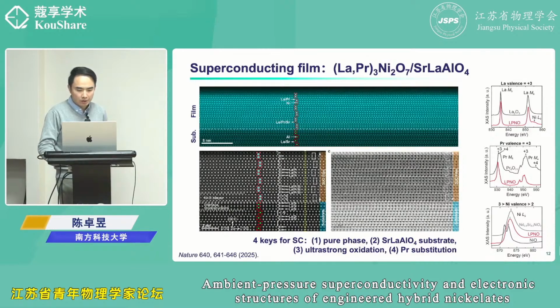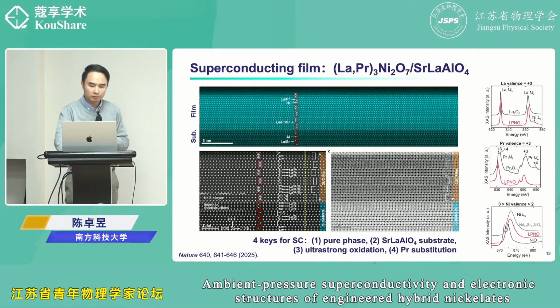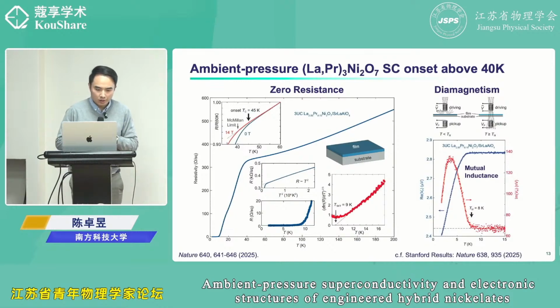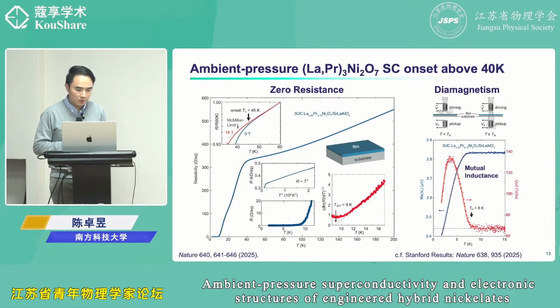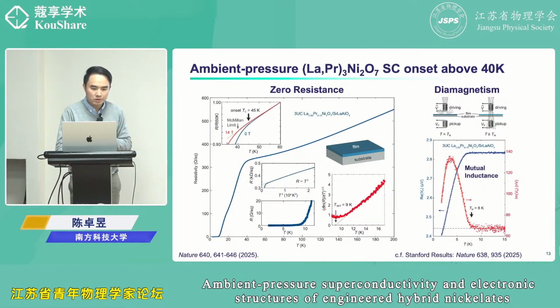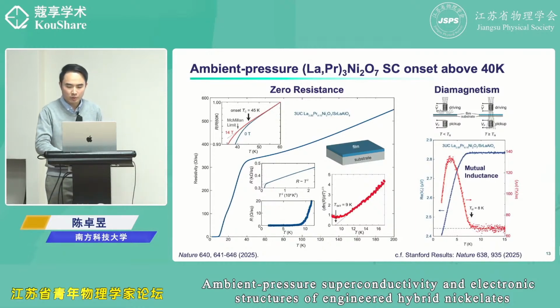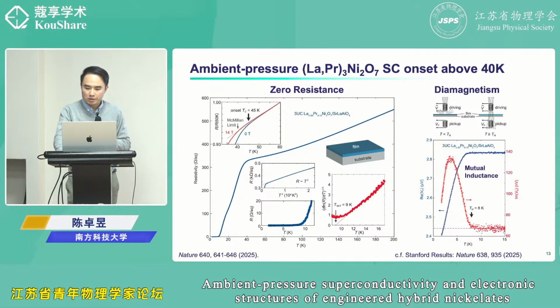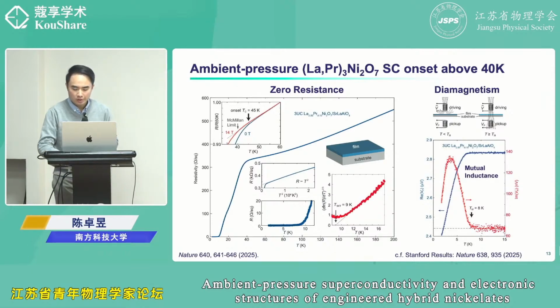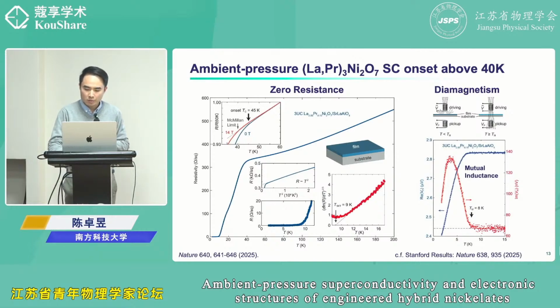So we guess the ionic size may be important, but maybe more important is that praseodymium's integration with oxygen is better. We achieve zero resistance and also diamagnetism within the same sample, and the onset temperature is slightly higher than the McMillan limit. And this is a definite proof of superconductivity at ambient pressure. Stanford also reported similar signatures using a different method, the original traditional PLD method. So both these results together confirm the Ruddlesden-Popper nickelate superconductivity under ambient pressure in thin film form.